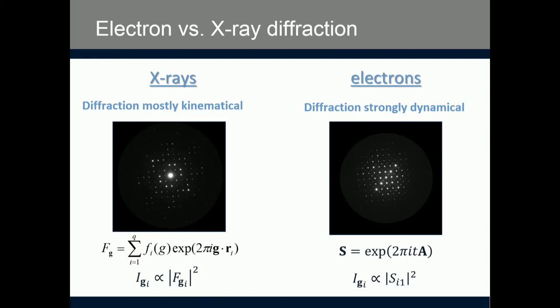This kinematical approximation is very well fulfilled for X-rays, and the slight deviations from it can be corrected by extinction correction in most cases, while it is not fulfilled for electrons. The quality of the kinematical approximation is much, much worse for electrons. The diffraction is strongly dynamical, and therefore the calculation of intensities is different.